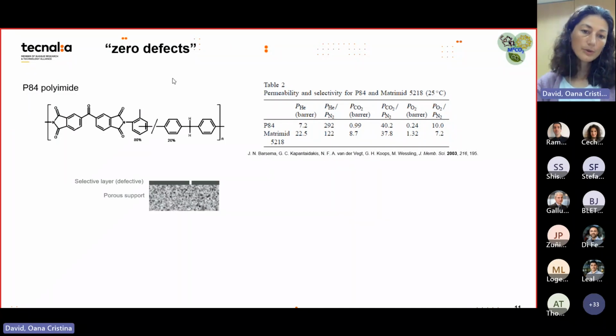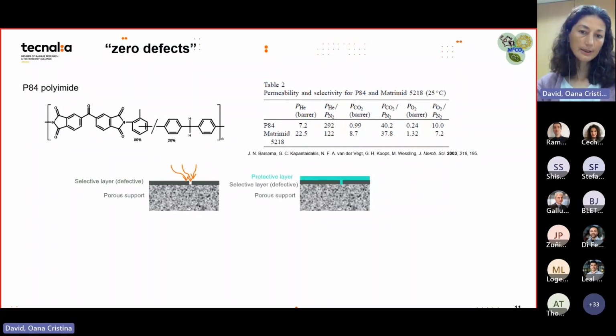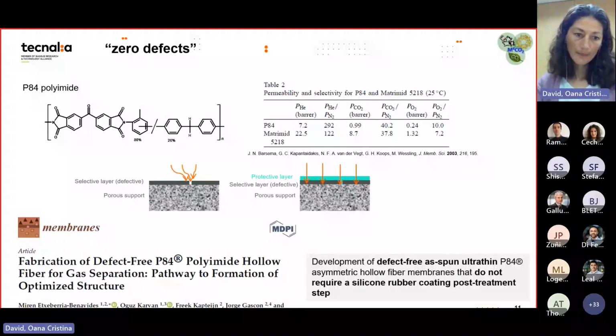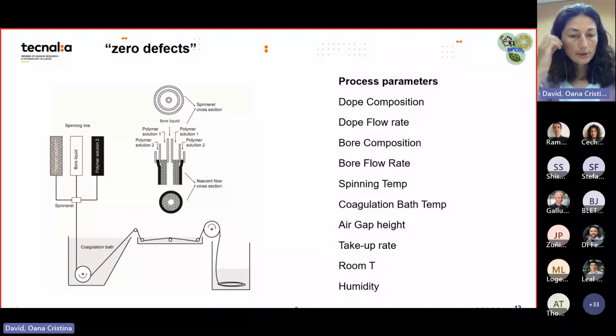Normally when you make monolithic hollow fiber membranes, you can have some defects on the outer skin. From time to time you have a pinhole in this dense layer, and here a PDMS layer as a protective layer can actually seal these defects. So instead of having air, you have another material here, which is PDMS, and this has the advantage that you can still use the selectivity of the rest. So the pinhole is not decreasing the selectivity of the material a lot anymore. But we actually managed to have these P84 polyimide monolithic hollow fiber membranes without any defects, and now I will show you how.